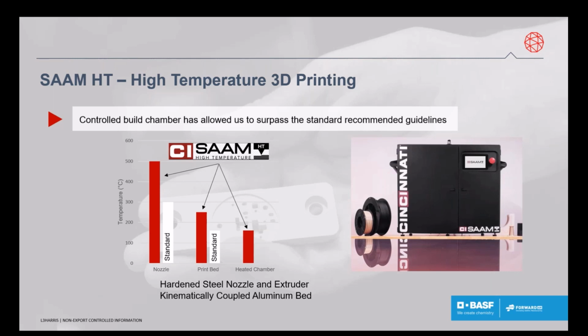We're running the hot end at 240 C, the table at 100 C, and the chamber at 55 to 70 C. The controlled chamber also allows the humidity within the chamber to drop to 10%. The nozzle we're using to print with is 0.4 millimeter.